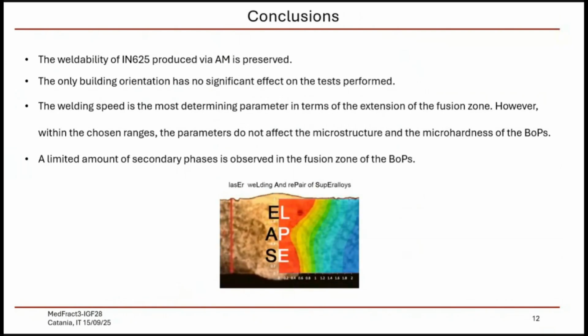So to conclude, the first important thing is that the weldability of IN625 is preserved, even if the fabrication process is additive manufacturing. The building orientation hasn't got a significant effect on the tests performed, and not even the process parameters, with the exception of the welding speed on the fusion zone extension. But we have to remember, this considers only these tests and the ranges investigated. And finally, we also found a limited amount of precipitation of secondary phases in the fusion zone, and this is important to know because these phases, these intermetallics, are detrimental for the integrity of the joint. They increase the fragility, they might be a problem for the weldability, so this is also good news.